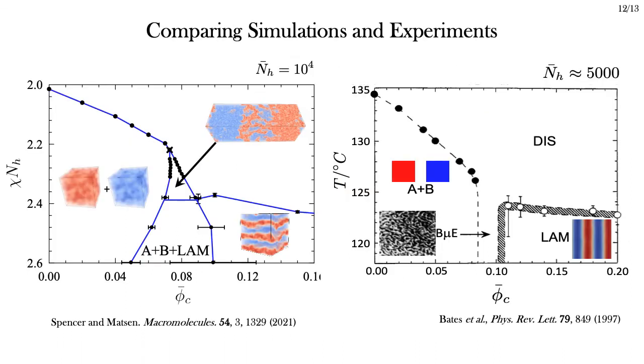Comparing our result with experiments, the big difference is that we don't see their microemulsion channel. Instead, we see this three-phase coexistence region. We believe that the simulations are correct, and this difference can be explained by metastability effects in experiments.